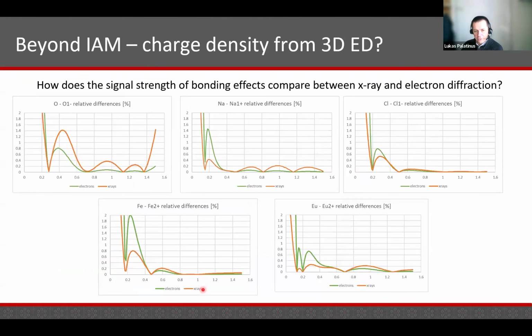And finally, I see that the hour is almost over, but I want to say a few words about probably the most challenging crystallographic investigation you can think of, and that is charge density analysis from diffraction data. Charge density analysis means seeing effects of interactions between atoms, effects of electrons moving from one atom to another in ionic bonds, or electrons shifting in the bond for covalent bonds. And here, again, at least in theory, electrons are better positioned to allow this analysis than X-rays. This is shown in these plots, which show the relative difference in scattering power between several ions, so oxygen, oxygen -1, sodium, sodium +1, and so on.